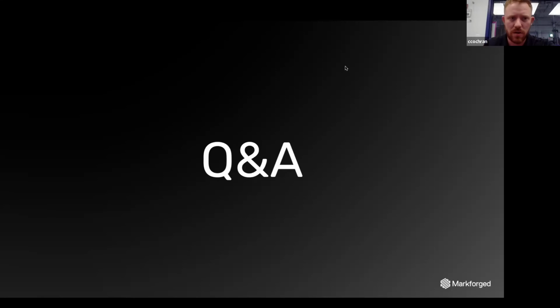that I give. So when I say plus or minus 1%, if we set up your blueprint, all your tolerances on there, we would account for the variation across production and say we need a tolerance of X, and it's mainly based on the size of your part, the size of that dimensional feature. And then sometimes if you have a really unique cross section, which plays influence into the densification, you have to do what we would call rescaling of the component, some localized scaling for your specific features. We'll say about 10% of our parts need that. 90% of our parts we can apply our general set of scaling factors that we maintain. Your part's going to come out great the first time.